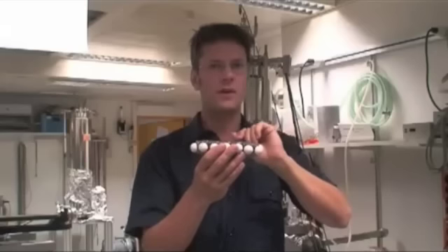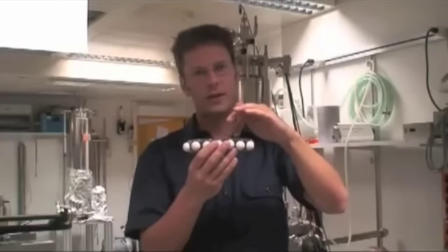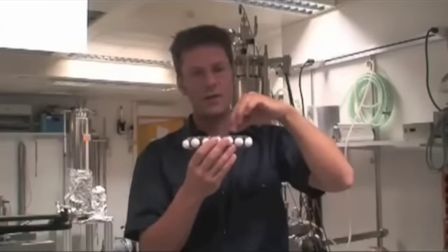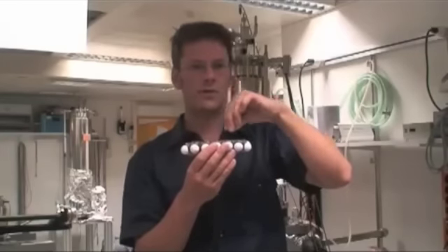And this is due to the Pauli exclusion principle. This happens when the electron orbitals of the CO tip and the pentacene molecule start to overlap, and then we get this Pauli repulsion.